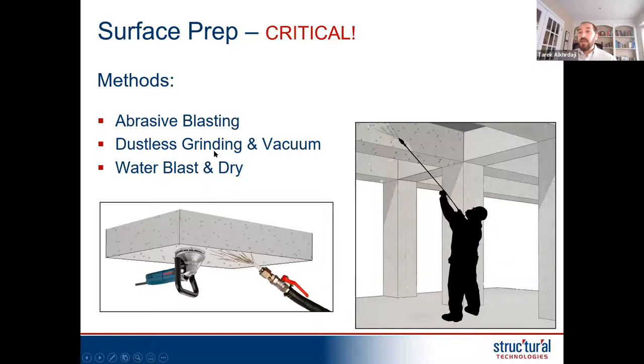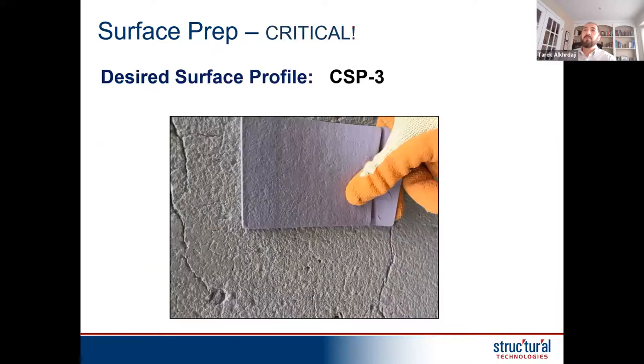Grinding has also been used a lot, especially for interior application inside buildings, where you basically grind with a special cup, a grinding cup, to make sure that the surface is cleaned. You remove a layer and still keep it rough to some degree. You don't want to create a very smooth surface. What we're trying to do is open the pores of the concrete so that when we put epoxy, it will penetrate through these pores, and that will allow us to get maximum bond to the substrate.